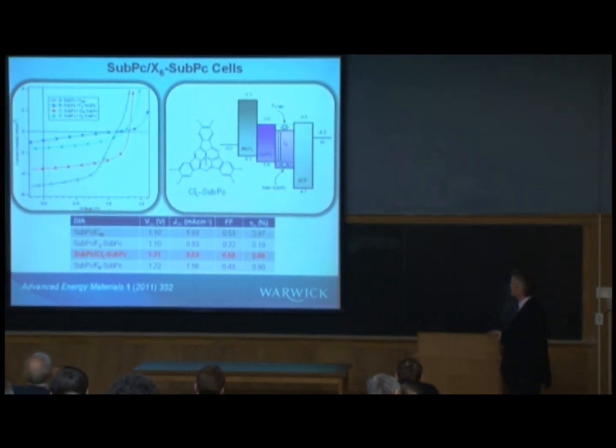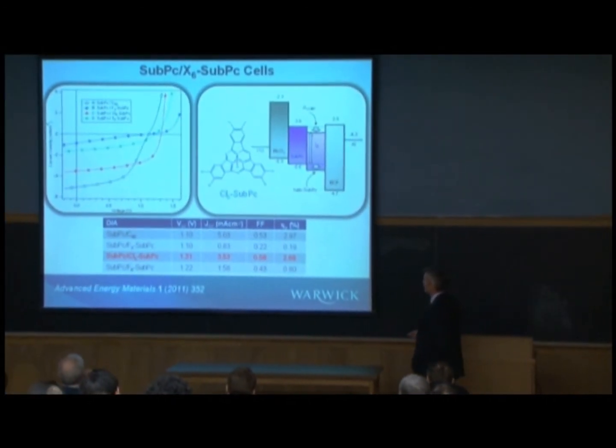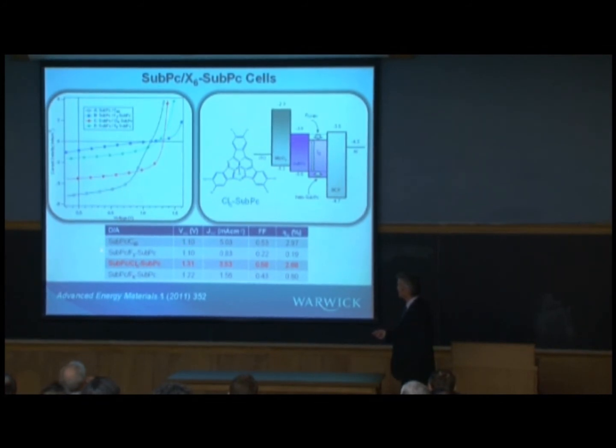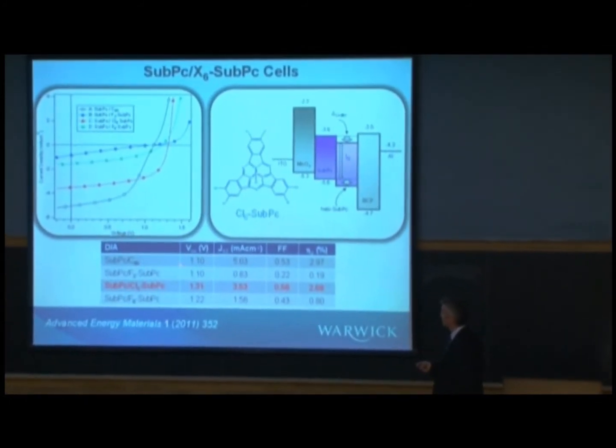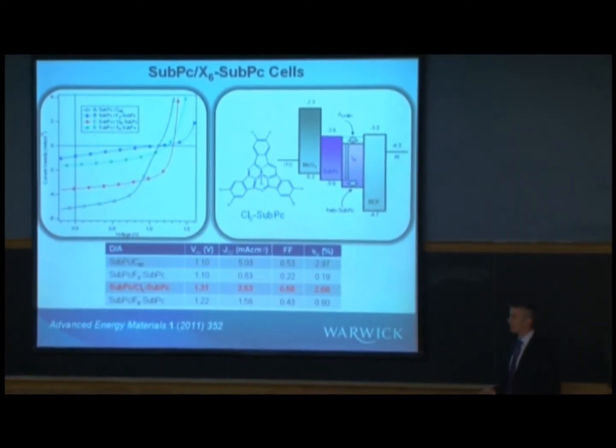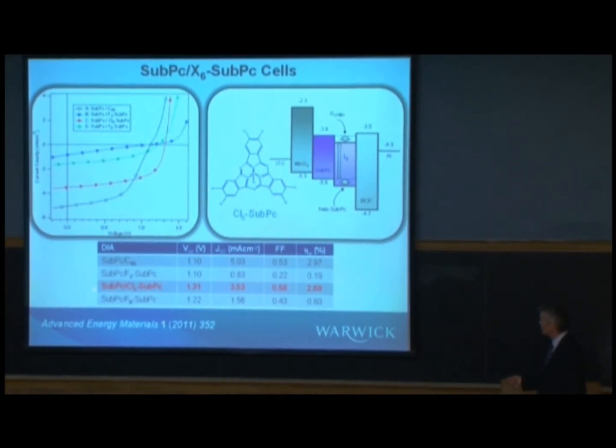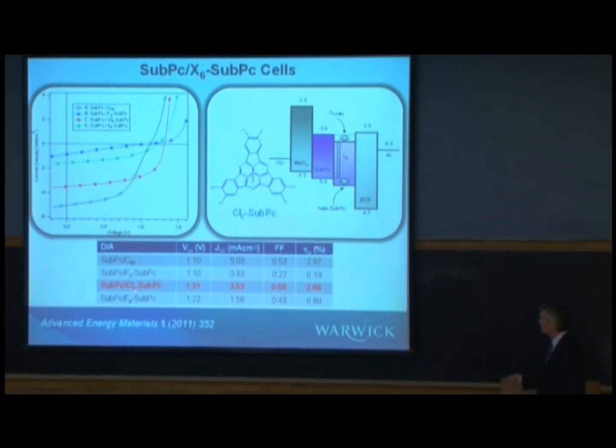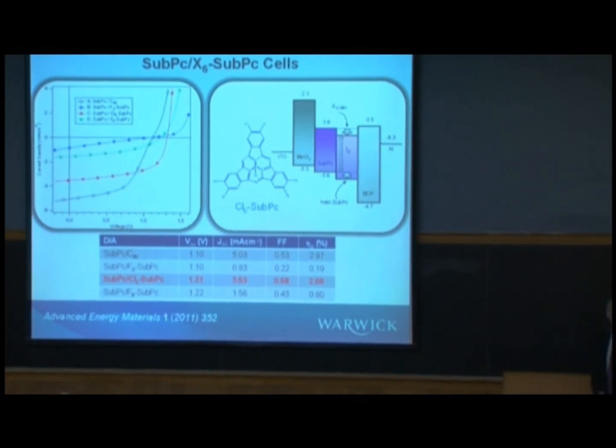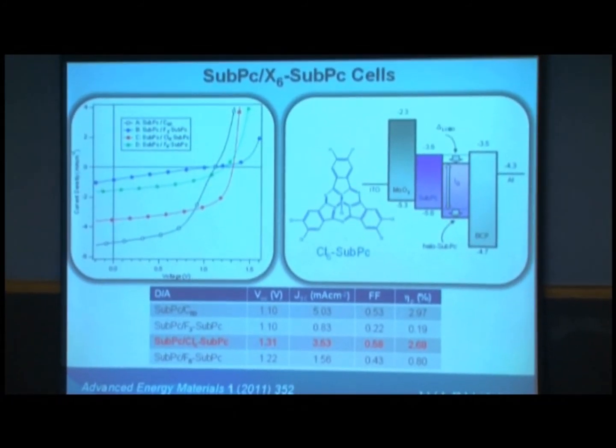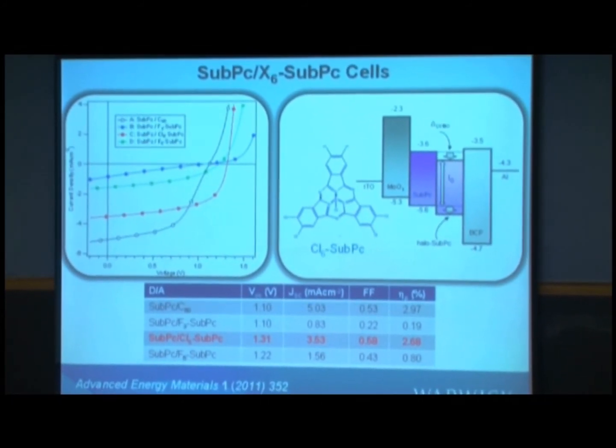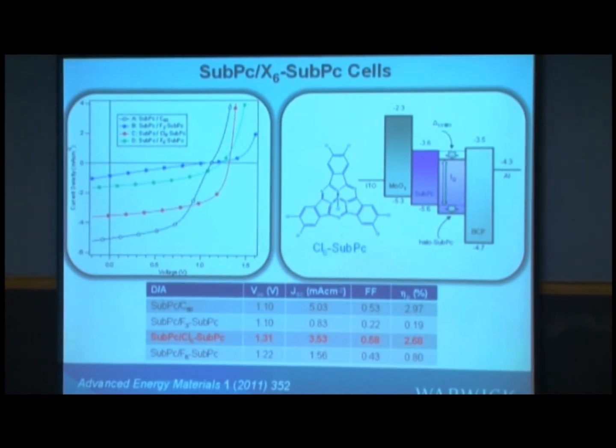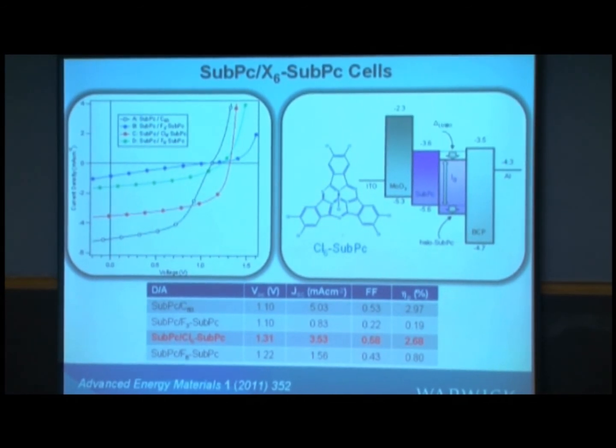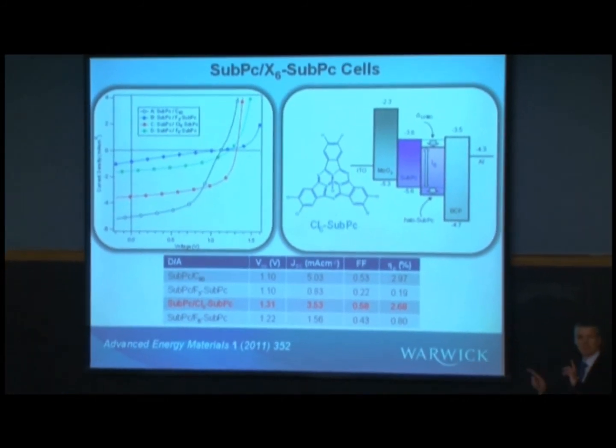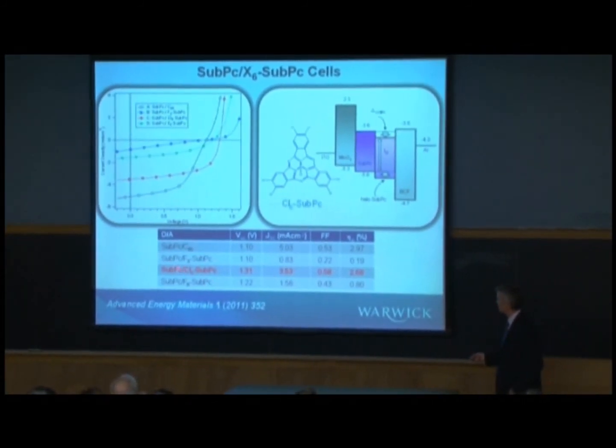So the example devices are shown here. This is our control device, subphthalocyanine C60 with a voltage of 1.1. And as we go across, we see the sub-PC with the hexachloro derivative gives a voltage of 1.31, which certainly at the time, and it may still be, I think, the highest voltage recorded for an organic solar cell using essentially the same class of materials, but one substituted with these 6 chlorines.